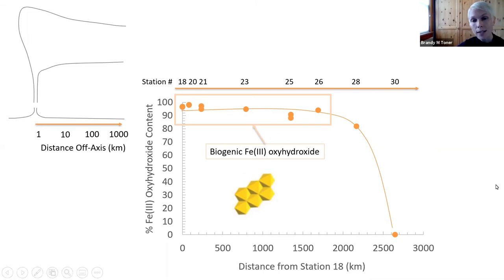The XAFS tells us that there's sort of these two-dimensional materials. You really can't call them a mineral in a traditional sense, but that signature, we can track it from the vent field itself and follow it almost 2,000 kilometers off axis. And this material appears to be stable. It's not aging, ripening, reprecipitating into other more stable phases.